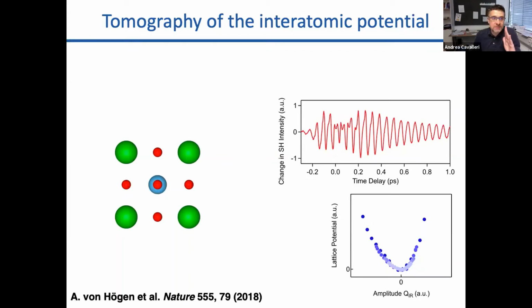So in principle, this could be seen as a way of measuring the interatomic potential that certain atoms feel at amplitudes that are far larger than the ones that are usually achieved by doing measurements such as neutron scattering or other inelastic probes such as Raman scattering. Of course, normally, if I look at the line widths in neutron or Raman scattering, all I will know is the way the potential looks very close here to the equilibrium point. But by this large excitation, one can find ways to map the interatomic potential down to third, fourth, fifth order expansion, and then compare this to, for example, ab initio calculations.